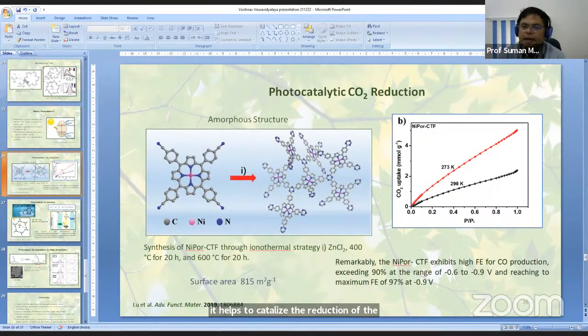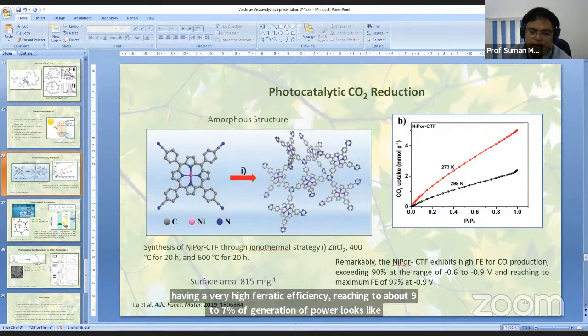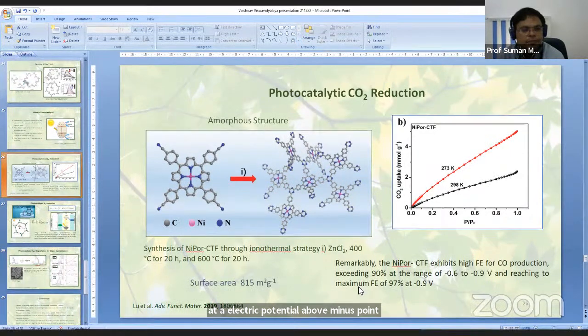So this is carbon dioxide uptake. As this is a porous network, it can trap carbon dioxide from the atmosphere. You can see at a lower temperature, it can trap almost 4 millimole per gram. At room temperature, it can trap about 2.5 millimole per gram. And then further, in presence of electrical impulse or under certain potential difference, this particular CTF, that is this photocatalyst, can show production of carbon monoxide from carbon dioxide, and it has a very high Faradaic efficiency, reaching about 97% generation of carbon monoxide at an electric potential of about minus 0.9 volt. So this is the first example, reduction of the carbon dioxide.